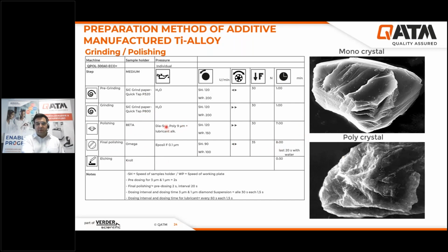Here you can see some words like poly, for example, diamond suspension poly or mono, or some words like this. I want to show you what it means. On the right-hand side, you can see the monocrystalline and polycrystalline diamond. As you can see, the polycrystal has more edges and is more aggressive than monocrystal. And to use the polycrystal, it is very important to have the right dosing parameters. For example, here you can see the dosing interval and dosing time for 3 micron and 1 micron is every 30 seconds for 1.5 seconds.